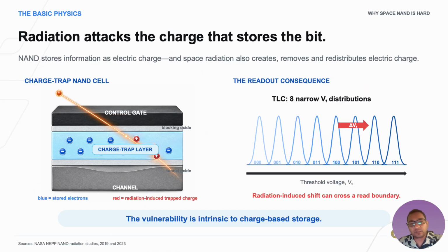Let's now move on to the question: why is space NAND hard? NAND stores information as electronic charge in the charge trap layer in the form of trapped electrons or holes. Those charges are very sensitive to radiation. Ionizing radiation creates electron-hole pairs, changes oxide and interface trapping, and can remove or redistribute the charge that represents the data. The resulting electrostatic change shifts the cell threshold voltage. In triple-level cell NAND, 8 narrow threshold voltage distributions encode 3 bits per cell. A radiation-induced shift can move a cell across a read boundary, so the controller interprets the cell as a different digital state.